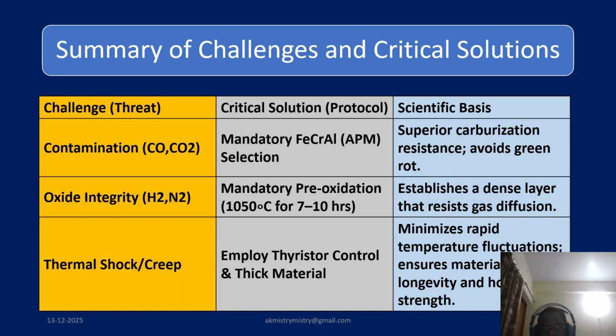So we are now coming to the summary. So to summarize the path forward, the threat of contamination, as we have discussed earlier, is countered by the mandatory selection of APM, ferrochromium aluminum, for its superior carburization resistance and its ability to avoid green rot that we have discussed in the preceding slide. The threat to oxide integrity, hydrogen, nitrogen, is countered by mandatory pre-oxidation at 1050 for 7 to 10 hours, which establishes the necessary dense barrier. And finally, the threat of thermal shock creep is countered by employing thyristor control and using thick material which minimizes fluctuation and ensures hot strength.